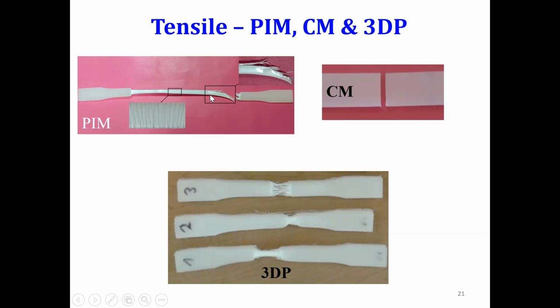Here there is a ductile failure. You can see these deformation marks, which we captured with micrography equipment or optical microscopes. Then if you take the same sample in compression molding, it is a perfect crack. So a ductile system transitions to a brittle failure, ductile failure to brittle failure, by just changing the manufacturing method. And if I change it to 3D printing, I get a failure pattern like this.